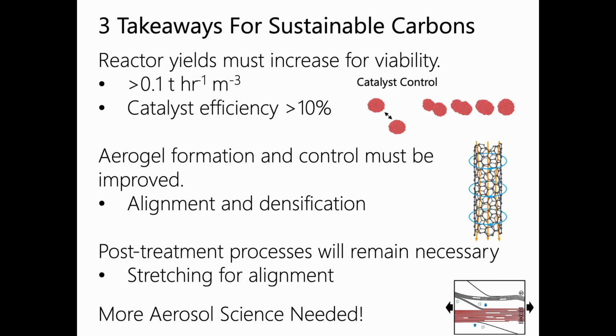And then I think ultimately our aerogel, the macroscopic assembly of these materials, will need to be controlled, and so electric fields are likely a way to do that in situ, just like the carbon fiber industry went and aligned material production at every stage of the overall process. We're going to have to do the same here to get high-end properties. And I think even with that, post-treatment processes will still be necessary to get the high-end properties. Now, we're not an order of magnitude better, but we're substantially stronger than steel, and so maybe there are lots of applications where you don't need to play some of these games once you get good at the others. So I still think stretching for alignment will be a game that we continue to play, and ultimately we need better contribution of all of the nanotubes within, so all of the nanotubes need to share the load, so to speak.